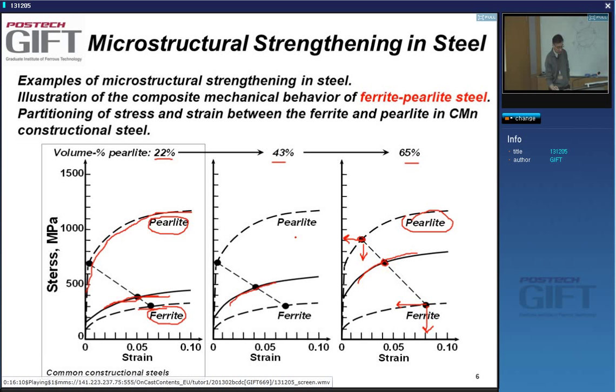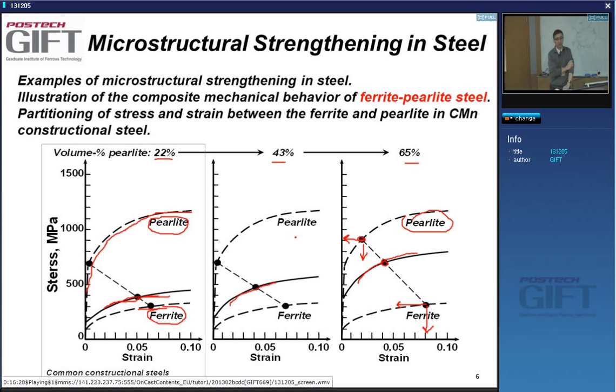In constructional steels, that's the trick people use to make different grades — they basically add more or less carbon. It's not the carbon itself that makes the difference, not even the cementite: it's the pearlite phase. Add more pearlite, get a stronger constructional steel. You can make very soft or very hard constructional steel, giving a very wide range of possibilities.